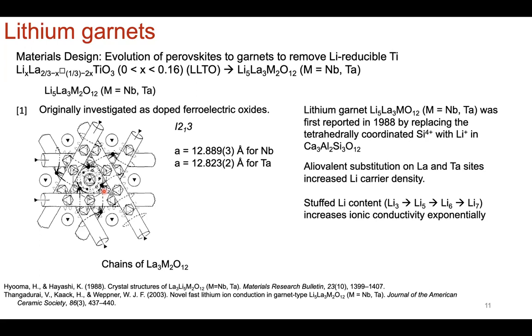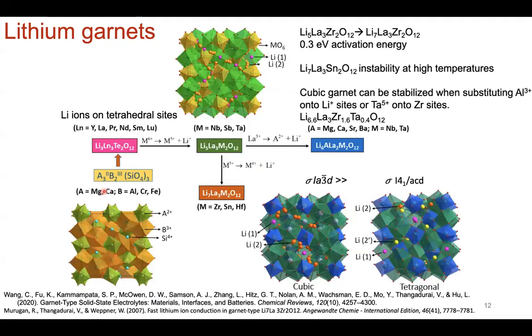And what people saw was that you can increase the ionic conductivity by stuffing or increasing. So I'm using just historical terms, that's not very scientific, but the historical term is stuffing lithium content 3 to 5 to 6 to 7. And it increases the ionic conductivity exponentially because it's increasing the percolative network of where the lithium ions are, but also it's increasing the disorder in the system, the crystal structure disorder, from lithium-3 all the way up to lithium-7. And so you can go from lithium-3 all the way to lithium-7 by this tree diagram that you see here.